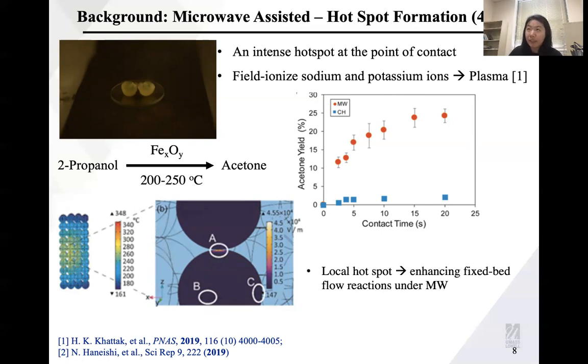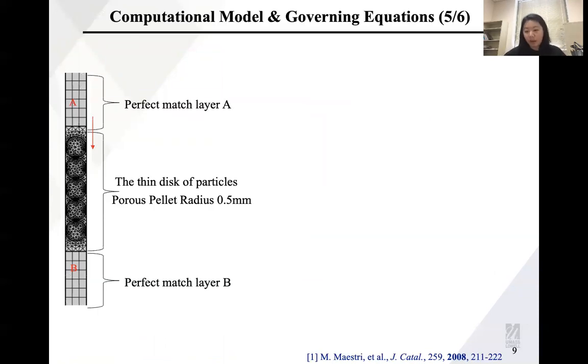So what we are trying to investigate in this project is what the dominant factors are that lead to hotspot formation under microwave heating, and how this hotspot can enhance the kinetics of heterogeneous catalysis. And are there any numerical treatments that can handle hotspot formation inside the microwave reactor? The computational method we use in this research is multi-physics in COMSOL, approximated by the finite element method. We are simulating five particles contacting each other to represent the packed-bed reactor, with the microwave input from the top layer to the bottom layer. This is a periodic setup, so you can imagine an infinite size in the X and Y directions of the packed-bed reactor.